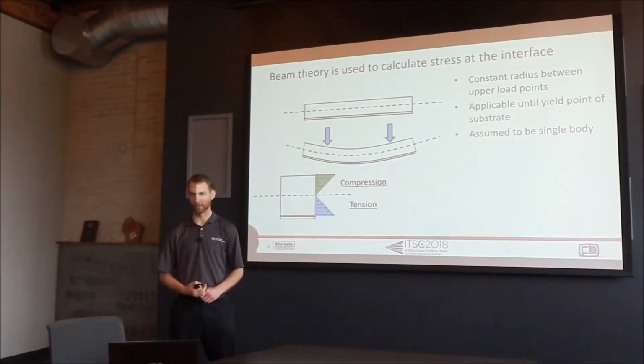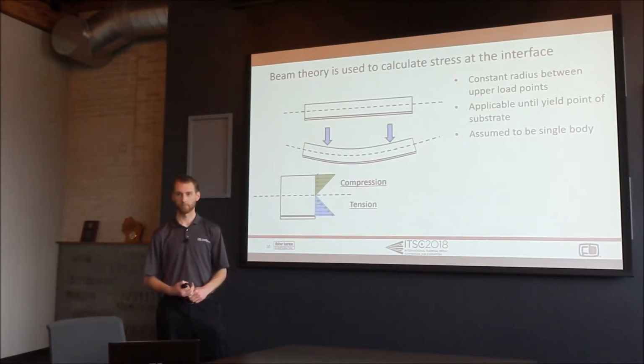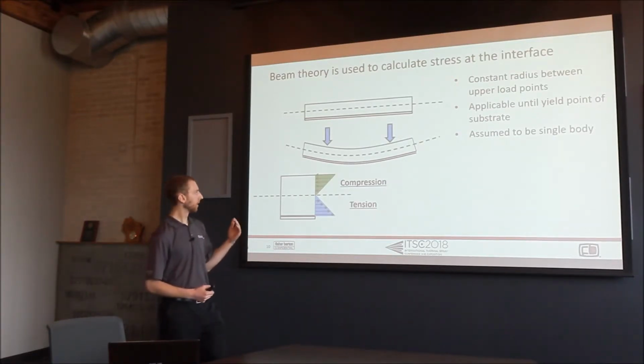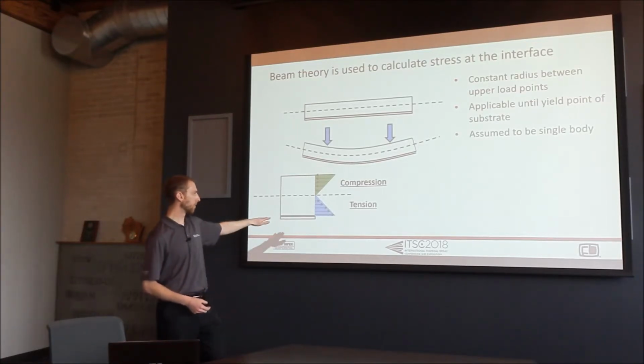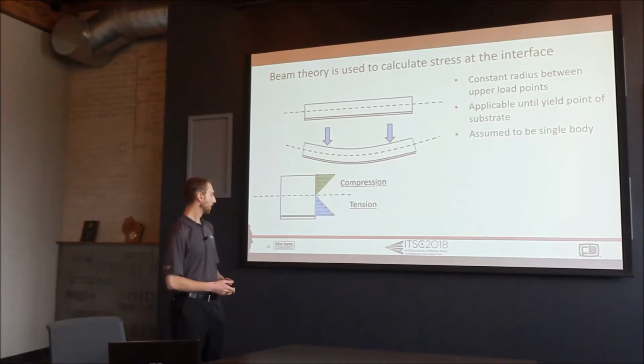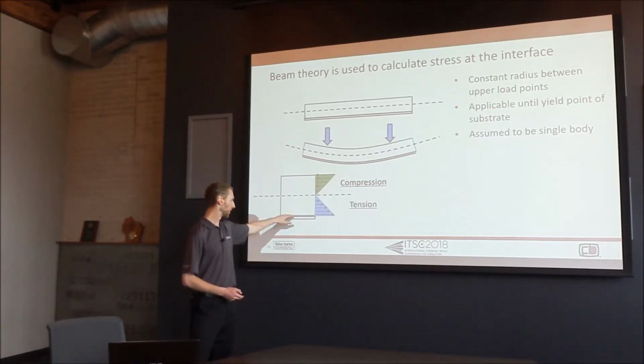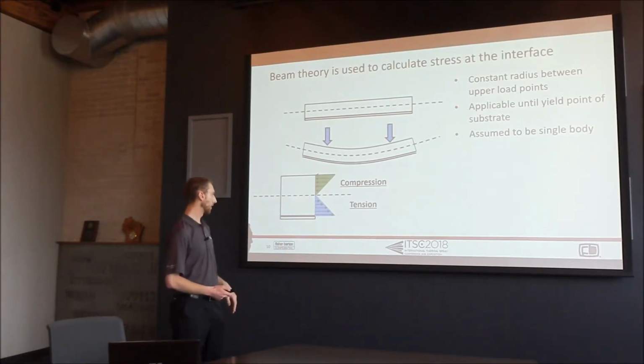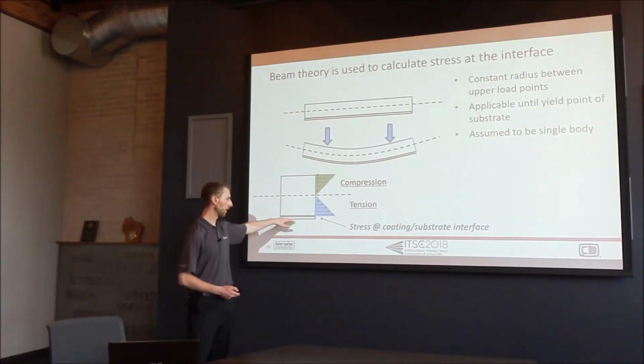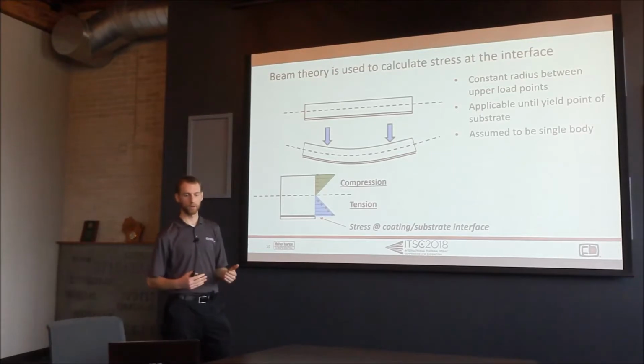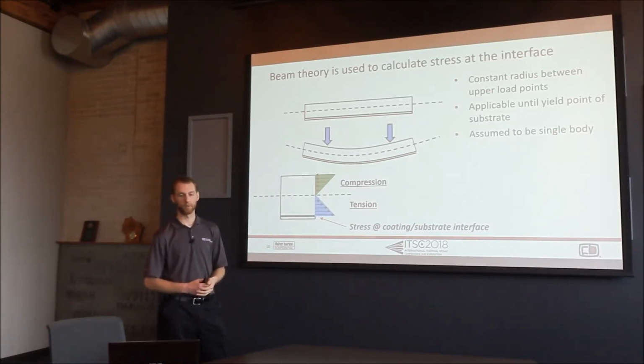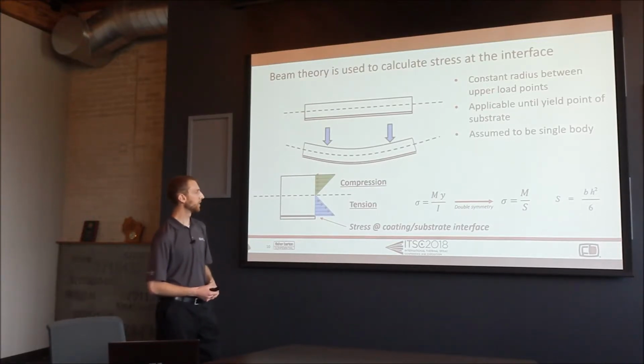For us to calculate the stress at the interface, we're using beam theory and the flexure formula. As that beam is bent downward, we're putting the bottom side of the bar under tension and the top side under compression. The stress that we're calculating is right at the interface between the coating and the substrate, and our strain gauge is applied at the surface of the coating. So there's a little bit of a disconnect there, as our strain is not at the exact same location. But again, we're using the strain gauge to show if there's adhesion or lack of adhesion at some point. And because of our pretty simple geometry, the beam theory equations are fairly simplified to the moment over the cross-section stiffness. So, fairly simple math.